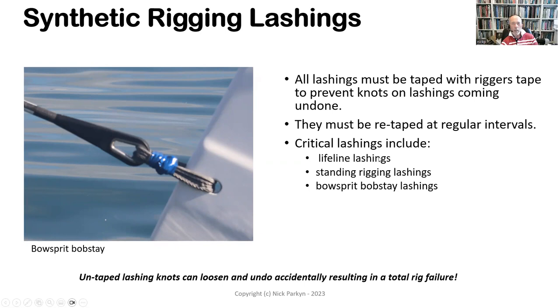Critical lashings include, of course, lifeline lashings and standing rigging lashings, as we said, which are often used for things like rotating masts, where we're not actually using turnbuckles. And here is actually a bowsprit bobstay lashing on a racing trimaran. But of course, remember that when we're underway, there's a lot of water lapping up the bow here, which would again tend to potentially disturb this lashing. And remember, any one of these lashing knots coming loose could result in a total rig failure.